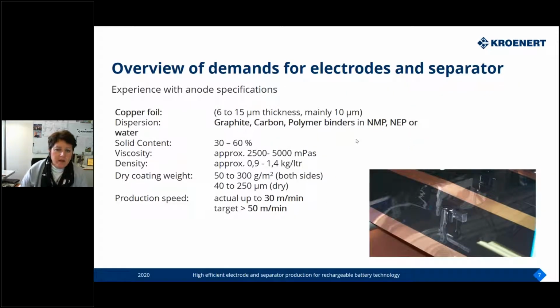When we go to the anode, it's usually a copper foil, so a more sensitive material. Also, it's quite thin, much thinner than the aluminum foil. So we handled already 6 micrometer thin foils, which is very sensitive material. And here also NMP, NEP, or even water is used for the binding of the chemical solution. The solid content is probably a little bit lower. And also the viscosity is in the same range as for the cathode.